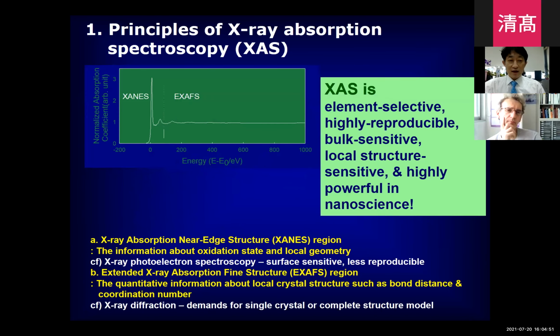As you know very well, X-ray absorption spectroscopy is very powerful in material science and nanoscience. XAS is element selective and highly reproducible, which is very important for me because, like many others, we frequently use XPS to determine the bonding nature of the material, but it is terribly not reproducible, because XPS data can be easily modified by the condition of the machine and the treatment of the surface. So I love XAS because it always gives very reproducible data.